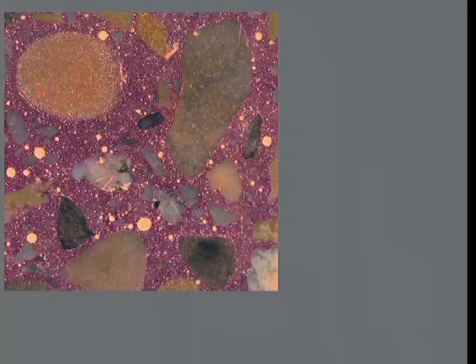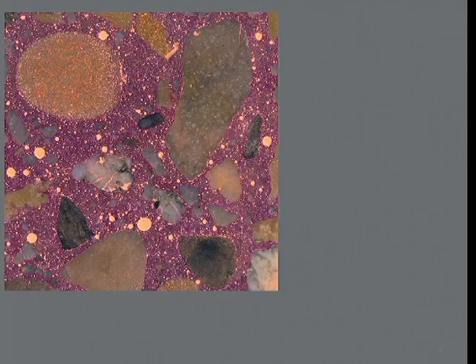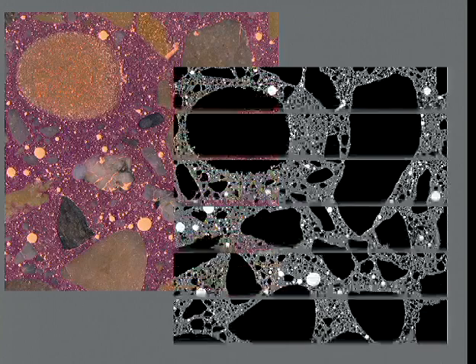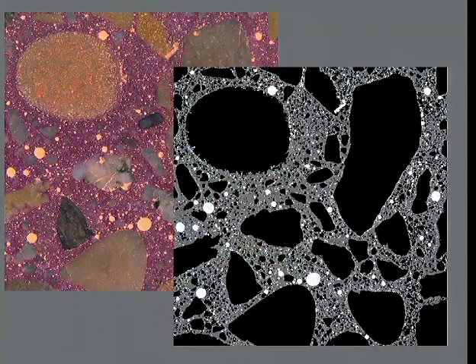Here's a diagram, a picture of microstructure to give you a little background about how we measure these things. And this particular picture shows how we're using a flatbed scanner and we're dyeing the paste surface with this pink dye, and the orange bubbles are illuminated, and we can get a scan of microstructure that gives us three phases: the aggregate, the gray in between is the paste, and then the white is the air bubble. So we did thousands of these images to characterize many, many different samples.